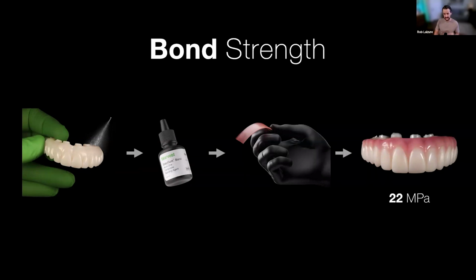It is a really intense bond strength. This is like 4 or 5 times the ISO standard. The ISO standard, I believe, is 5 megapascals. And so 22 megapascals is an incredible bond strength, but you got to follow the process in the IFU.